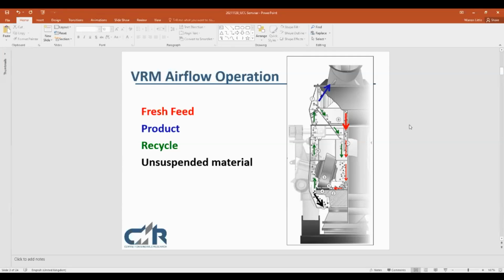So just one other thing to point out here is that there's a little black arrow there at the bottom, unsuspended material. If any material in airflow operation is too coarse to be suspended by the flow of air, it falls to the base of the vertical roller mill and then is recycled externally. When we look at operating this machine in overflow mode, this is the stream that we are making use of. We don't push air through the mill, so there's no suspension of particles within the grinding chamber, and all the particles fall to the base of the mill and then get recycled externally, passing through external classifiers.